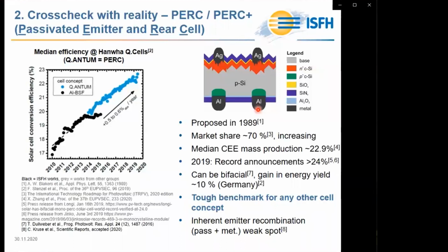All these features together make the PERC cell and this specific contact combination a very tough benchmark for any other cell concept. Nevertheless, it also has some inherent weak spots, in particular the recombination in the phosphorus doped n+ region, in the passivated regions, but also and in particular in the metallized regions, is significant and poses a certain efficiency limitation.